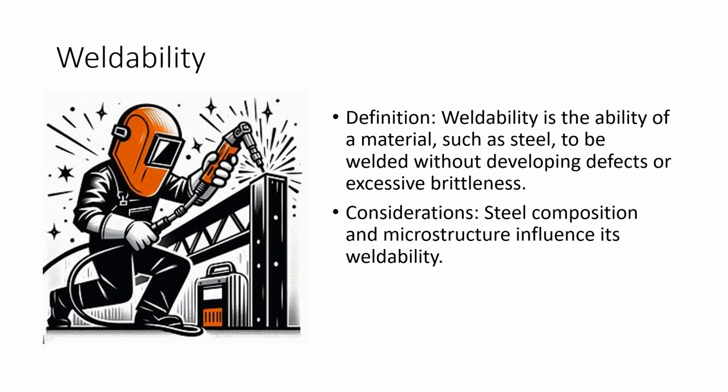This stuff is because you've got to preheat it a lot, and then when you cool it down, you've got to add a lot of heat to it. Then you let it sit for a while, then you do a hydrogen bake out so you don't get cracking, and then you send it to the heat treater, and then they cook it for a while. So it's just nasty. But it's not a very weldable material. You really got to have your act together if you're going to weld that material. So a lot of the considerations for this are steel composition and microstructure. They influence the weldability of a material.